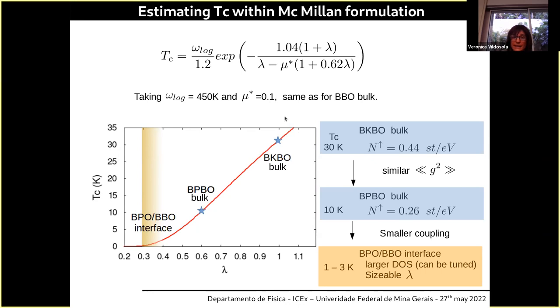And if we put in this BBO family, bulk, which has the highest critical temperature of 32 in bulk, we have a density of states of 0.44 states per electron volt. And when it is doped by potassium, it has a similar matrix element as when it is doped by lead. But what makes the difference between these two systems is the density of states at the Fermi level, that in the case of lead decreases to 0.26. So the critical temperature decreases from 30-something to around 10 kelvins. And in the case of the interface, depending on the width of the lead layer, the critical temperature can vary from 1 kelvin to 3 kelvin, as was experimentally observed.